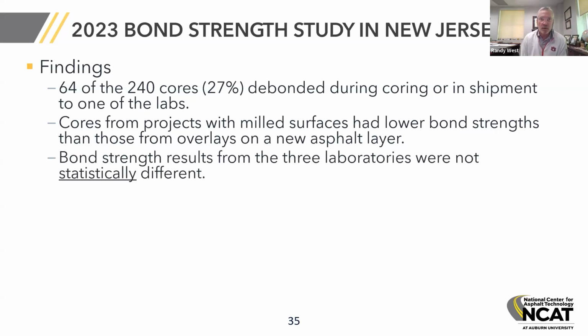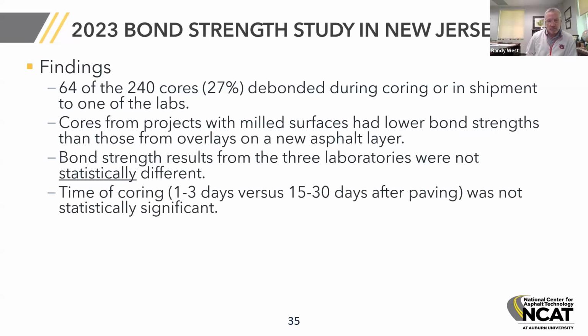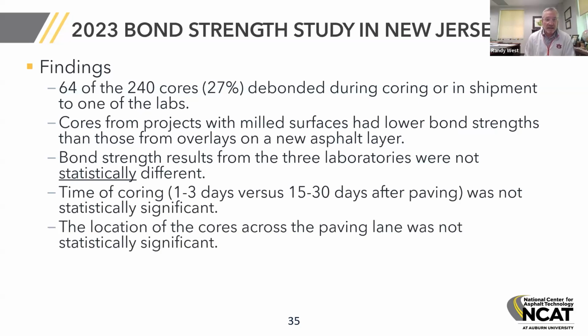In terms of the analysis, we saw that bond strength results from the 3 laboratories were not statistically different. There was some bias, but they were not statistically different because there's significant variability with bond strength testing. We did see that the time of coring, the 1 to 3 days versus 15 to 30 days, also was not statistically significant. And lastly, the location of the cores across the paving lane was not statistically significant. That was a surprise to me.